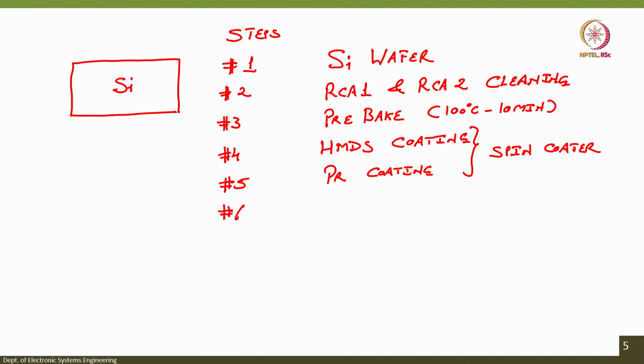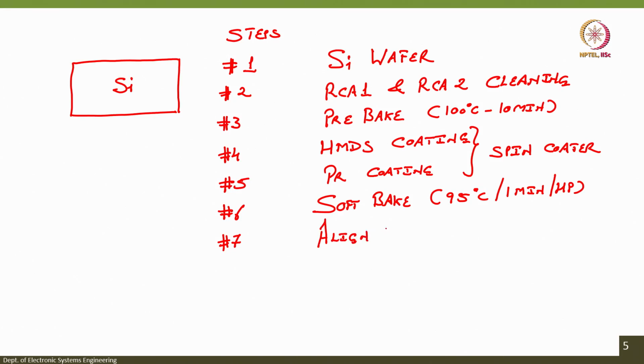After PR coating, the next step is soft bake. Soft bake is done at 95 degree centigrade for 1 minute on a hot plate. Next step, mask alignment of the wafer with respect to the mask, and UV exposure.